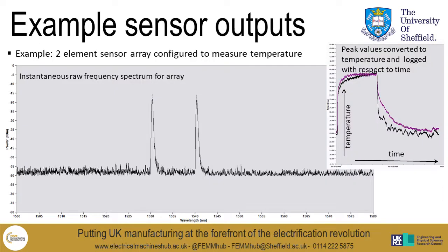Okay, so this slide shows an example test of a two-element FBG array. You can tell that it's a two-element array by looking at the frequency spectrum that's obtained from it. You can see in that spectrum quite clearly that there are two very distinct peaks, one relating to each of the two FBG elements within the array. What we then did was apply a temperature stimulus to both of these sensors and record the resultant transient response. You can see in the figure on the right the inferred temperatures which were obtained from this test.